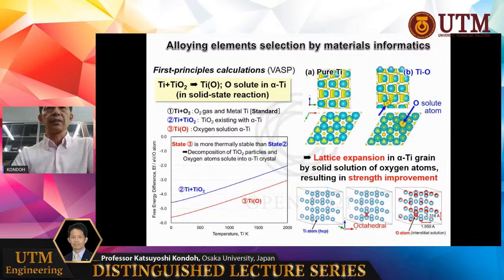For example, on the right side, I show that in the case of the titanium oxygen combination, oxygen atoms exist as interstitial solute atoms between titanium atoms, shown here. As a result, the oxygen interstitial atoms cause lattice expansion in the alpha titanium grain crystals. The lattice expansion causes large strains around the crystal. And finally, we successfully obtain the strength improvement. So in that case, the first principles calculation method is very effective to estimate which element is suitable or effective to improve the strength or mechanical properties of titanium alloys.